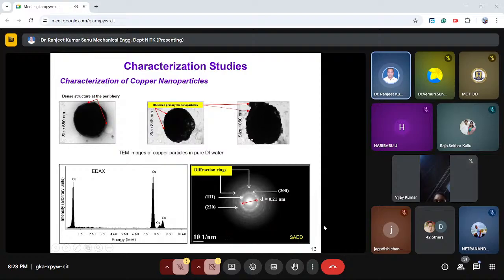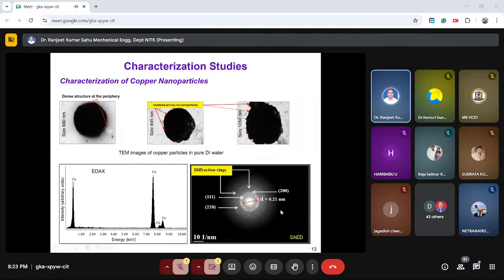Moreover, we carried out the selected area electron diffraction pattern to identify the crystal structure of these particles, whether it is oxidized or not. So you see here, these are the diffraction rings. This shows a sequence of electron spots, each spot related to a specified diffraction condition of the crystal structure. This shows clear diffraction rings. The diameter from the center to each concentric ring was measured. The first ring diameter yields a lattice spacing, d spacing, of 0.21 nanometer. That matches with the FCC crystalline lattice distance of 0.20 nanometer for the 111 HKL plane.